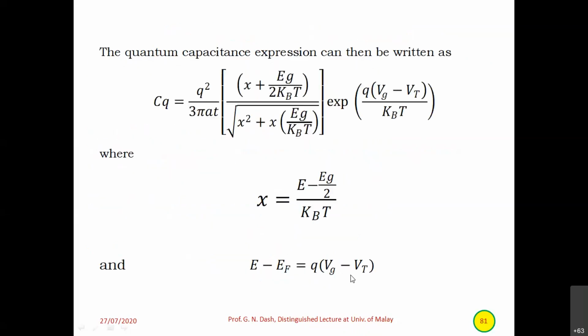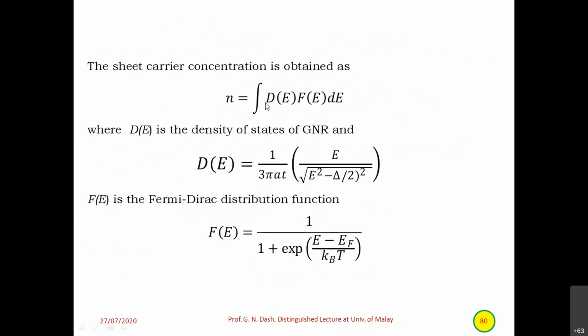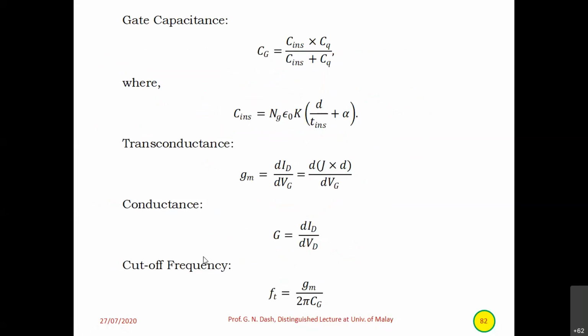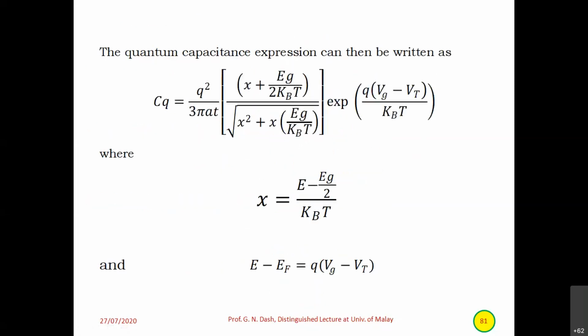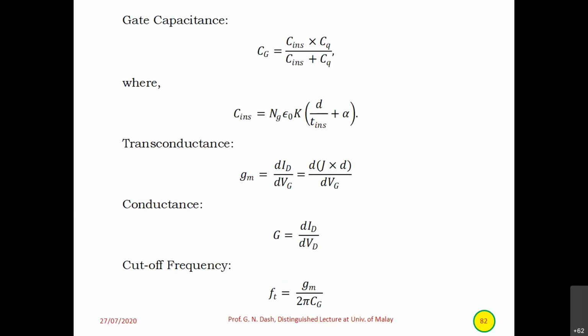So you can see this is the standard equation for calculating carrier density in a semiconductor, that is the density of states D(E), the Fermi distribution function f(E), and small q. This D(E) is the relation for a graphene nanoribbon, the density of states gives this relation, and the Fermi function gives this relation, and the quantum capacitance expression can then be simplified to this. The gate capacitance is the parallel of insulator capacitance and quantum capacitance, C_in and C_Q, no, not parallel, actually it is series, where C_in is given by the classical capacitance relation.